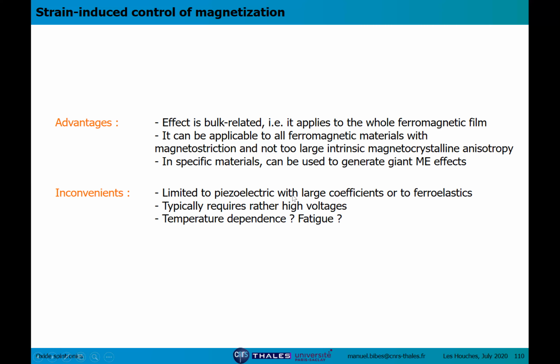usually most of the work has been done with bulk. If you want to go towards miniaturized devices, you want to work with piezoelectric thin films, which are much less easy to work with. And first you have to grow them. It's not easy. And typically you're going to need quite high voltages. And there's an issue with fatigue, because a lot of strain involves a lot of stress on the mechanical properties, and maybe fatigue occurs after a few cycles.